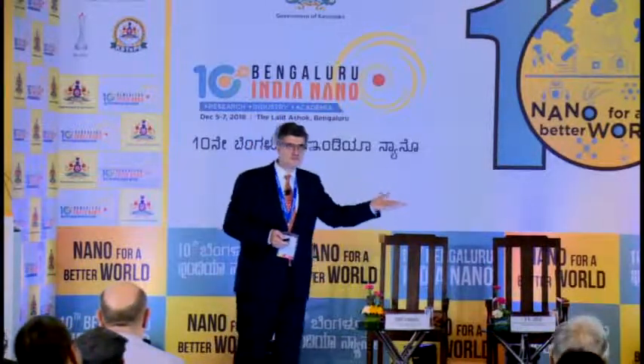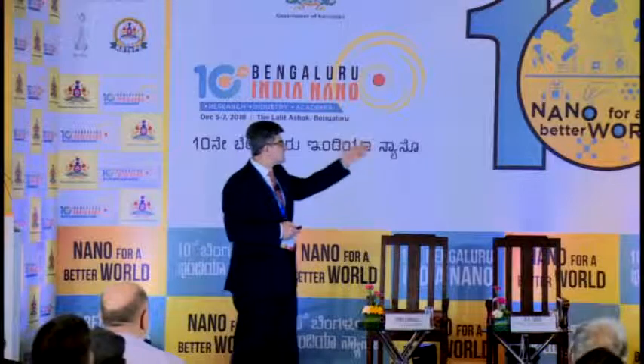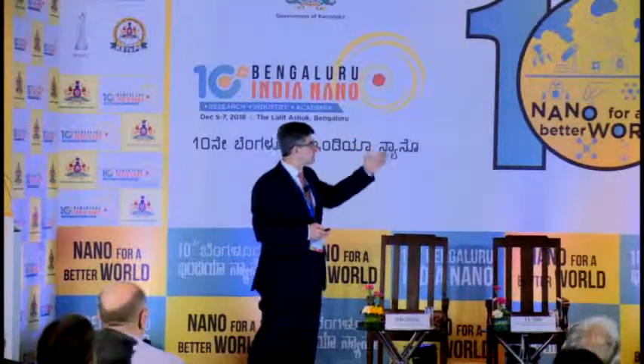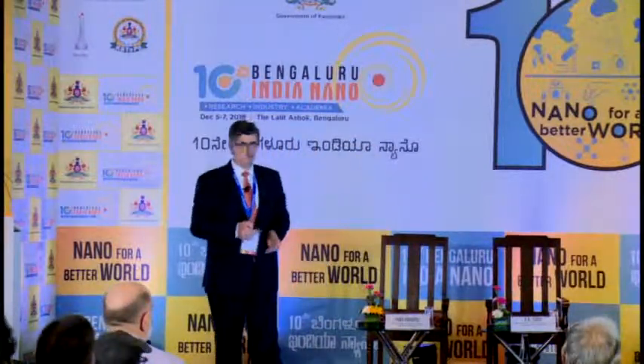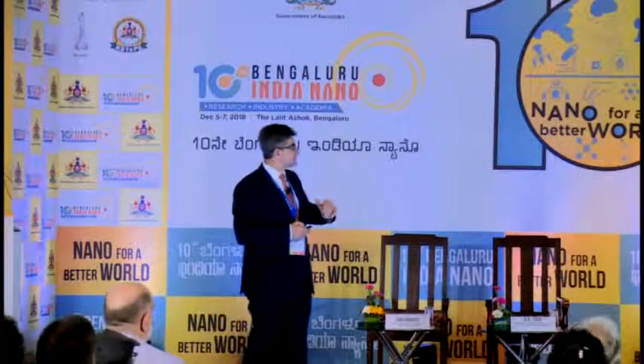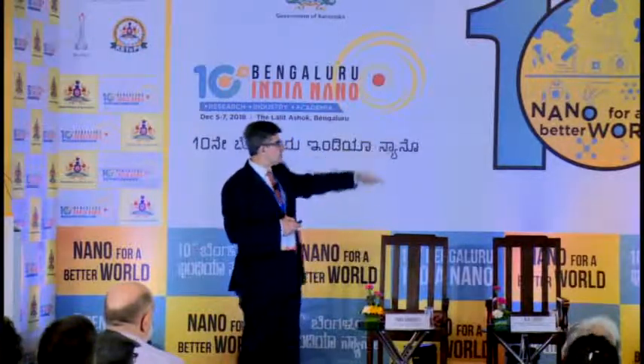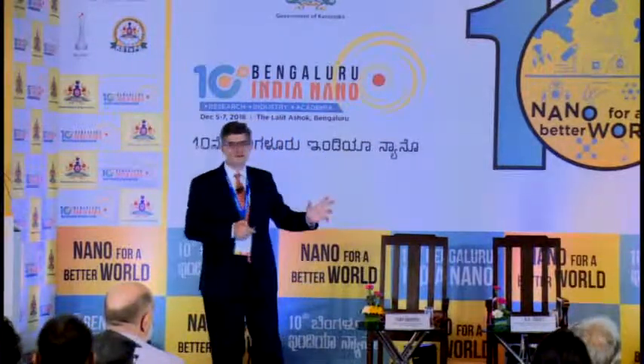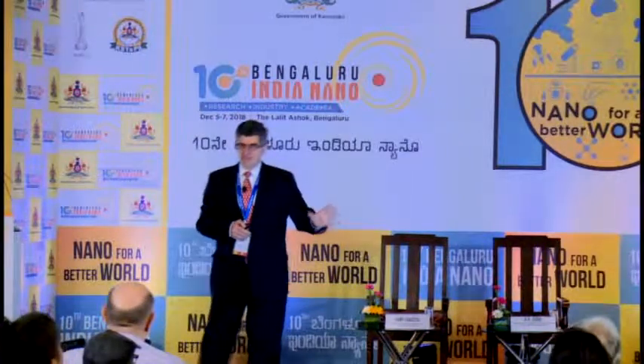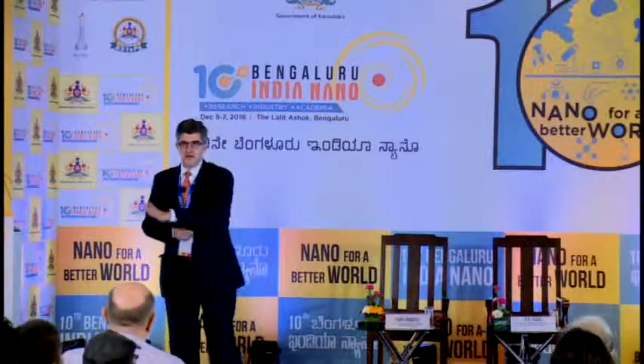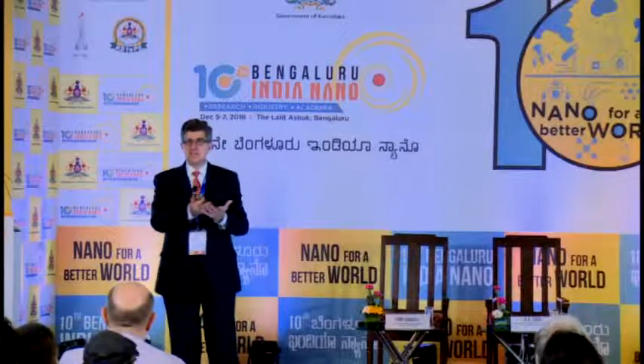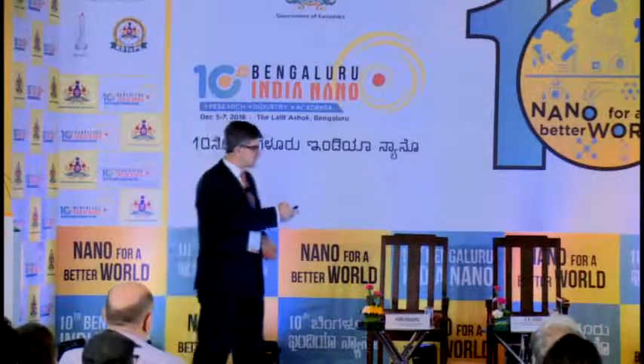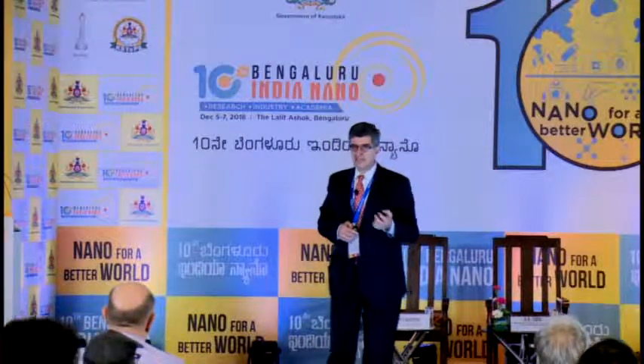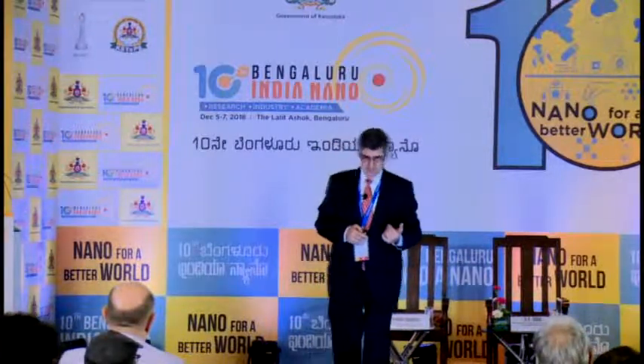We just take water, we get colloidal solution, we can spin coat it, spray coat it, dip coat it, vacuum filter, produce transparent conducting films, or produce a film by filtration, a thicker film, or we can take the slurry after etching, roll it through a rolling mill, and produce a film, which, you can see here from this middle image, is like a foil. It's metallically shiny.